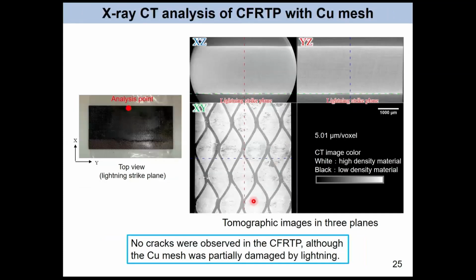And this is the result for the sample with metal mesh. In the metal mesh case, we cannot see damage inside the sample, no crack occurs, and also no delamination occurs. I thought it was a very great technique in that experiment. The metal mesh caused no damage.